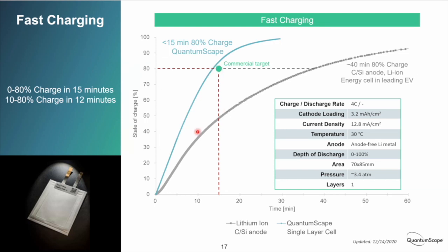What's shown in gray here is data that we didn't take in our lab, but found published on a leading automotive cell hooked up to a supercharger that in 15 minutes gets to about 50%. And then the charge rate really has to taper off after that to avoid this problem that I spoke of earlier of lithium plating. So to get to 80% takes about 40 minutes in these types of cells.